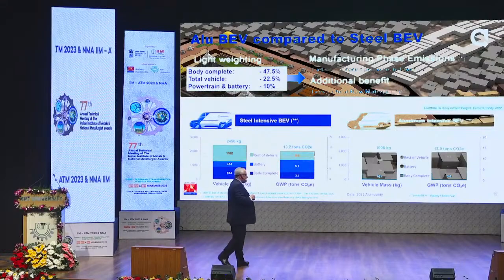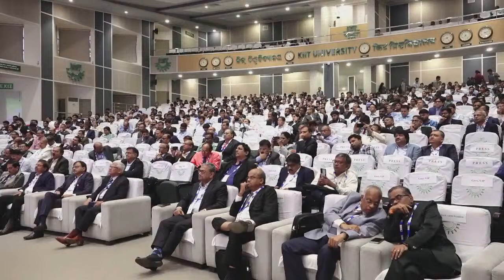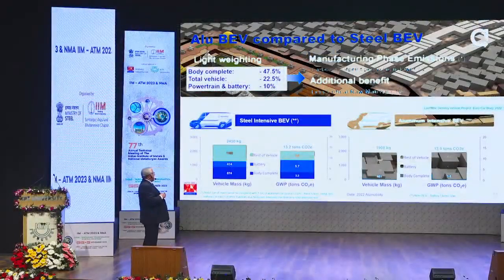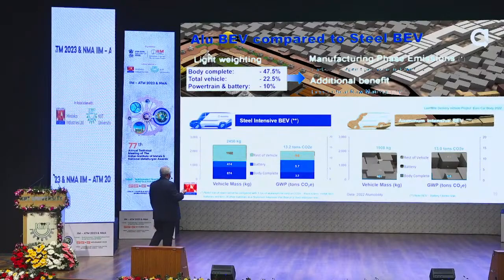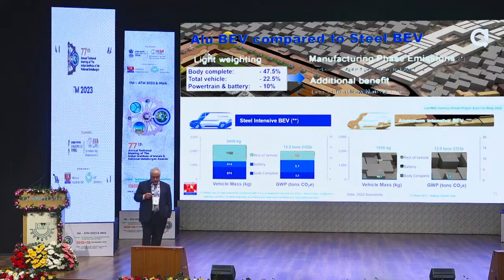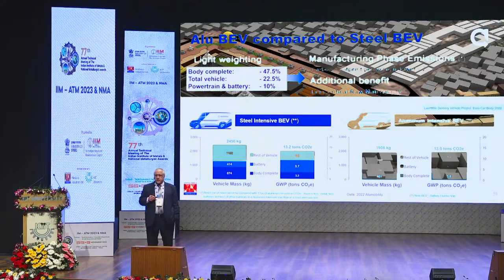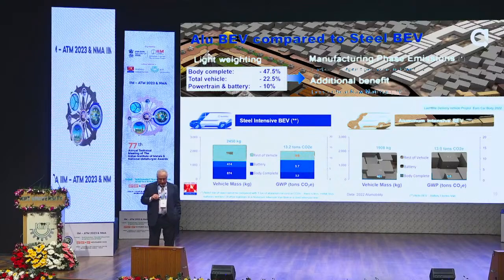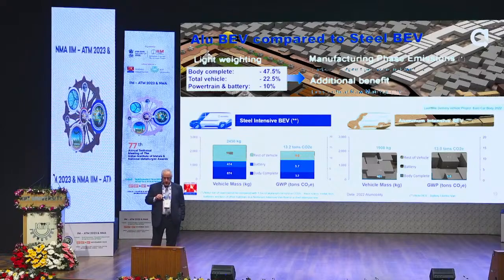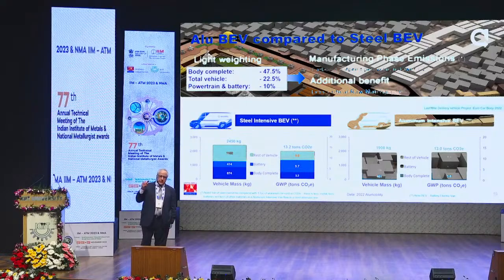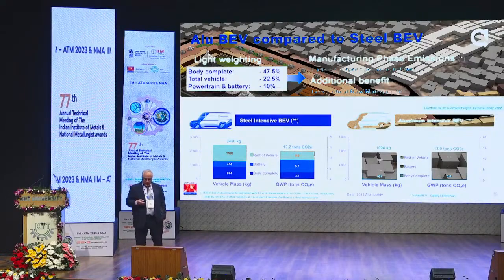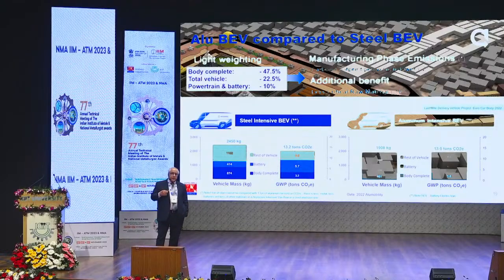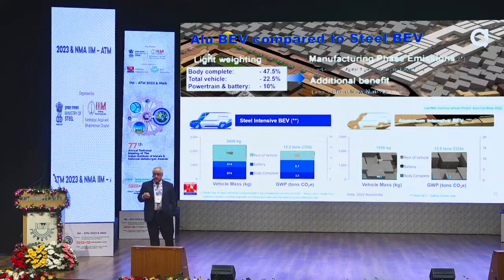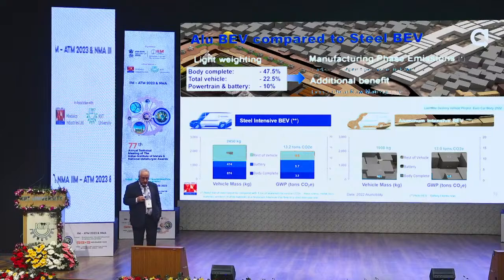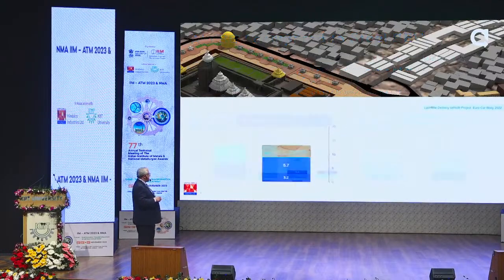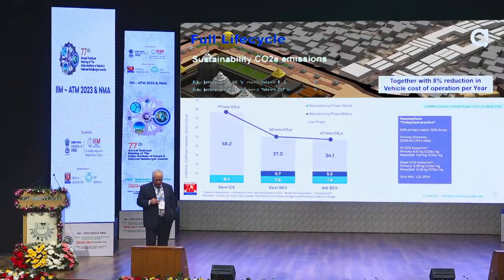Now, as we have to go quickly, I will just comment the conclusions of that. If we look at battery electric vehicles, fully aluminum intensive as compared to steel, what appears here? The body, again, for last mile delivery vans, you see again a 47% weight saving. Total vehicle is 22. But very important, we save in powertrain and battery 10%. It's 10% less of cobalt, of lithium, of rare earths, of whatever material is critical. And so the message here is already with the technology we have today, we can have a carbon footprint for the complete vehicle lower than with steel, and with additional benefit of reducing the content of critical raw materials.